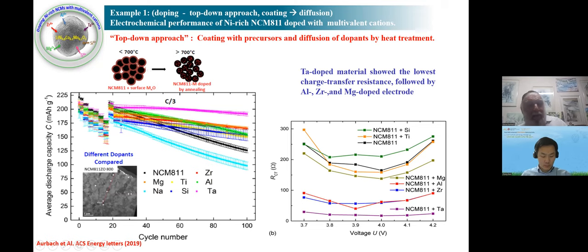But here, the top-down approach is we take precursor, we put it on the surface. Now we put it in solvent like ethanol, we dry the ethanol. Now we have a layer of precursor on the surface and we apply a high temperature. The high temperature forces diffusion of the metallic dopant inside, and we have also segregation. So we have more concentration on the surface. And in such a way, we have a doping of the material.